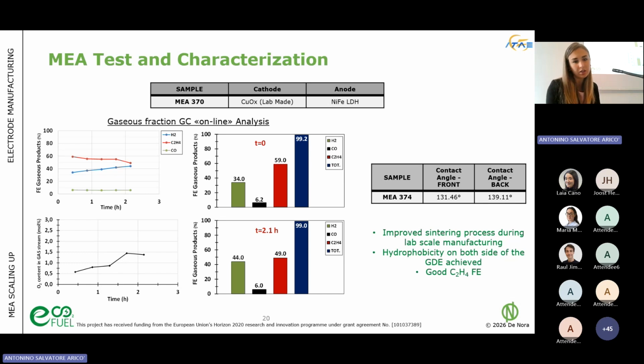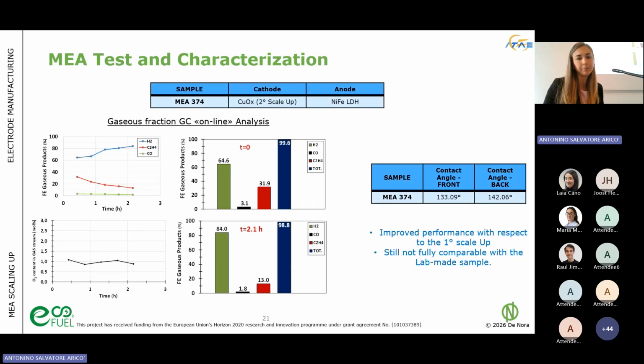We still have some hydrogen, but if we sum the ethylene and the carbon monoxide, we are over 60% production of gaseous carbonaceous product. So it's a very nice result. So we tried to reproduce this aspect at the industrial scale, doing this in the second scale-up. Still, here is what I wanted to pass on as a message: what we obtain in the lab is not always what we obtain at the industrial scale.